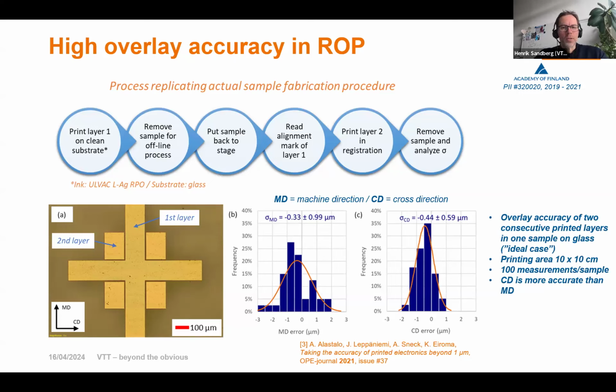This, of course, requires also very stable substrate material. So this is actually often one of the drawbacks, that the method is much more accurate than the stability of the substrate. So much of our work is now done on polyimide films, which are very stable, but we also do a lot on PET. But mostly we work on a few micrometer scale, not on the absolute minimum of the accuracy of the method.